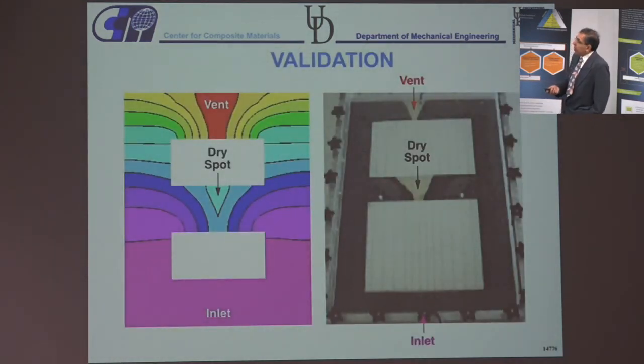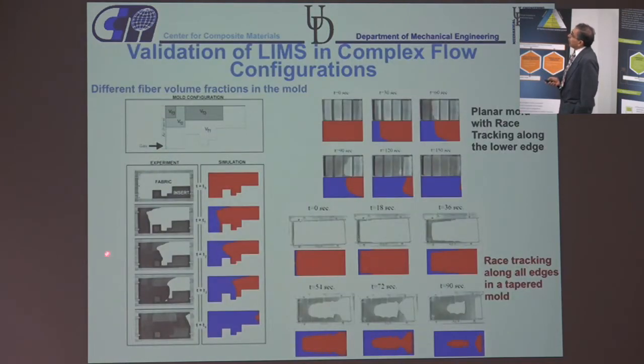Once we have the permeability values, we can run simulations, and over the years we have done many validations. This is a 6-foot by 3-foot part where we injected the resin from here, and we were able to map the flow fronts to what we saw in the experiment. Here are some other ones with different fiber volume fraction, and you can see the experiment on the left, the simulation on the right. Here you have race tracking along one edge where the resin is going faster, and we are able to even capture that.